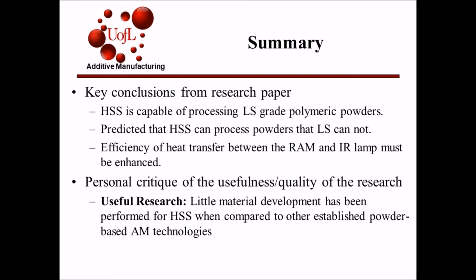Key conclusions from the research paper. It was shown that high-speed sintering is capable of processing laser sinter grade polymeric powders. Mechanical properties of the specimens produced by either process were similar enough to confirm this. The journal also predicts that there may exist some other powders that high-speed sintering can process that laser sintering cannot. Moving forward, to improve the mechanical properties of laser sintering grade powders that are processed by high-speed sintering, the efficiency of the heat transfer between the RAM and the infrared lamp would have to be enhanced.